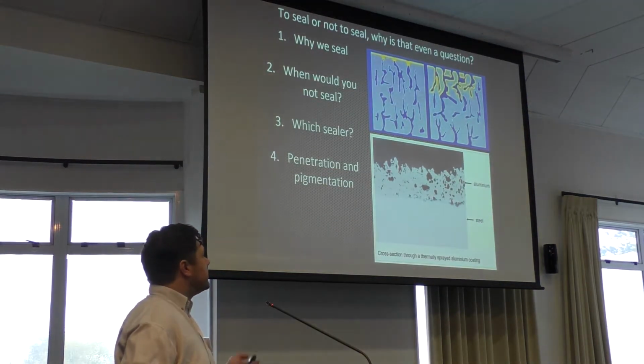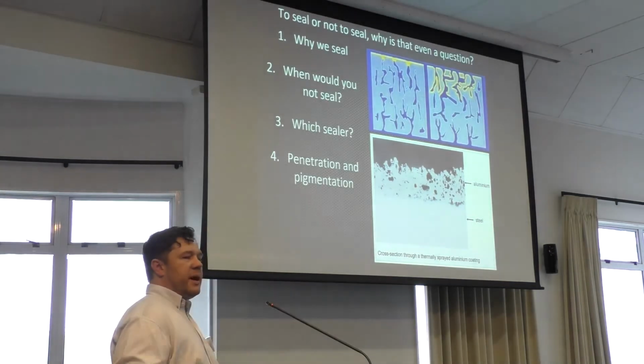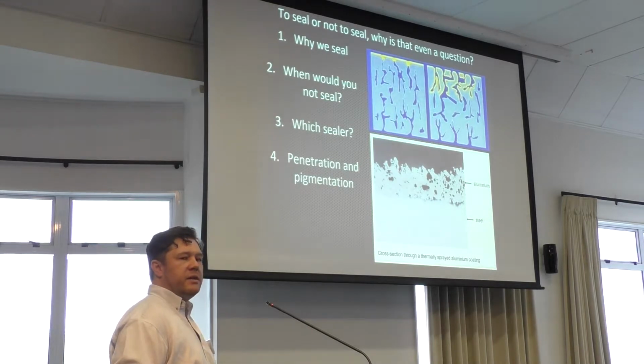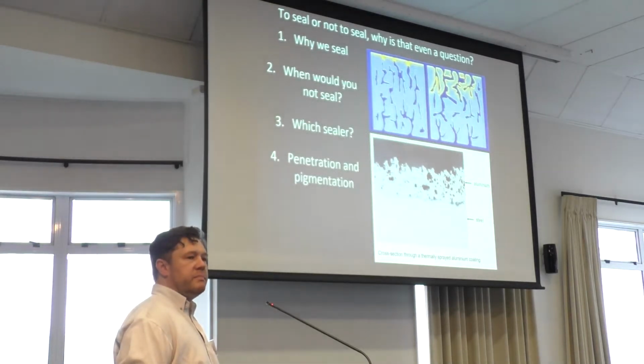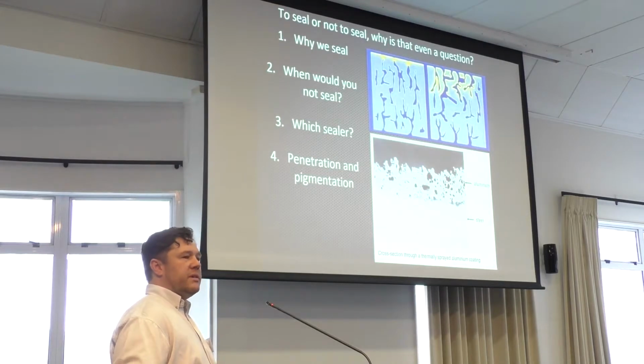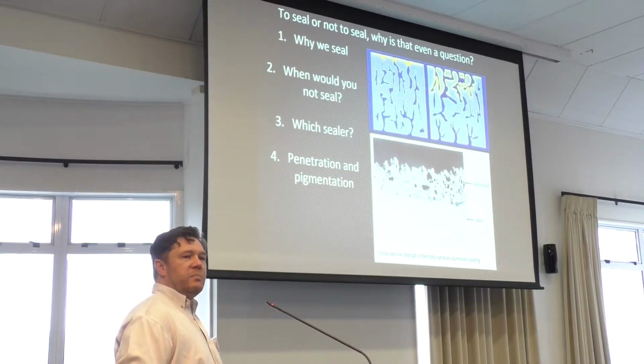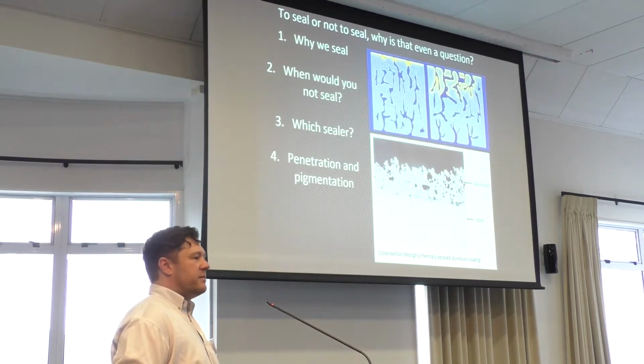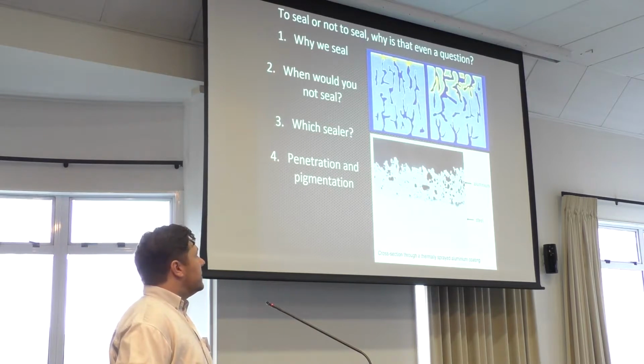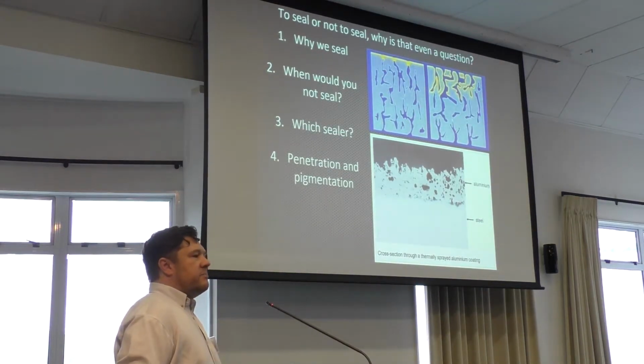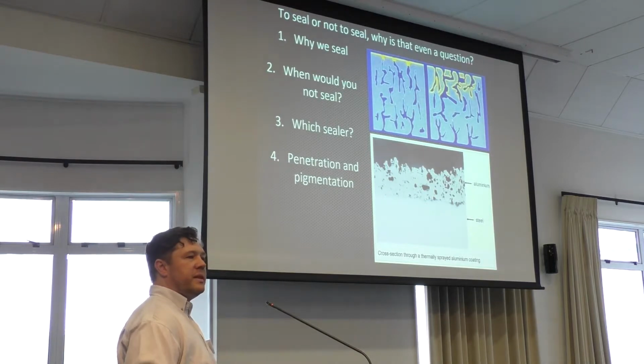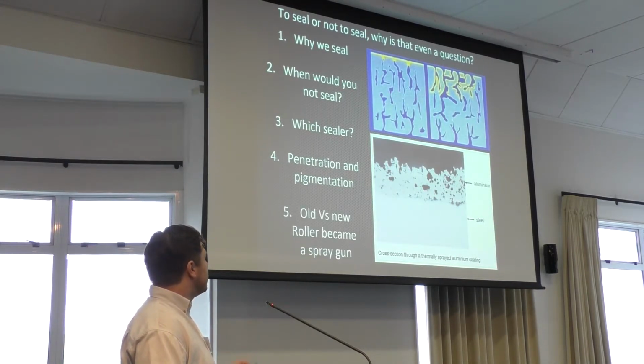The pigmentation can be an issue because the pigments in paints, a lot of paints are particles, and if the particle is bigger than the porosity in our coating, it's going to act like a plug and prevent the sealer from penetrating. So ideally we'd suggest to use a very slow drying non-pigmented sealer, which typically are expensive and nobody wants to wait around for them to dry, hence the vinyls. So by using the thinning, we can help get it in there quickly. And the thinning can also help avoid bubbles in the sealer after. I'll cover that a bit more later.